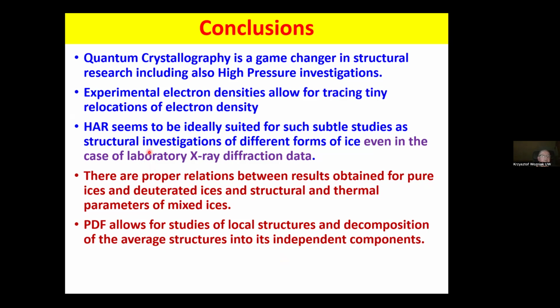by switching over to aspherical approaches, we can improve not only single crystal X-ray studies, we can improve powder diffraction refinements. We can improve pair distribution function. We can improve macromolecular refinements. We can improve also XANES and EXAFS outcome. We can improve cryo-electron microscopy results. We can improve electron diffraction results. So actually, we can improve the quality of structural data in general. And additionally, we can get electron density data, which are not accessible when using the independent atom model.